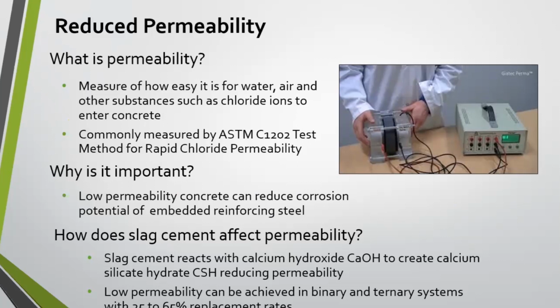So why is that important? Obviously, lower permeability concrete reduces corrosion potential, and we don't want that reaching the reinforcing steel. So how does slag cement help us when it comes to permeability? When we looked at the previous slide, we talked about slag cement reacting with the free lime, or the calcium hydroxide, creating more CSH and reducing the permeability. Low permeability can be achieved in binary and ternary systems with 25 to 65% replacement rates.